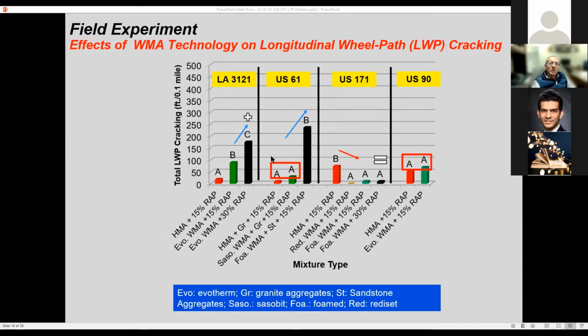Then we move on into intermediate temperature activities, and specifically, we're looking at the longitudinal wheel path cracking. And what you see in here is that the mixture that has 30% RAP had a significant increase in cracking. The mixture on US 171 is a conventional mixture. You look at the one that is the WMA, it has a significant decrease in cracking.